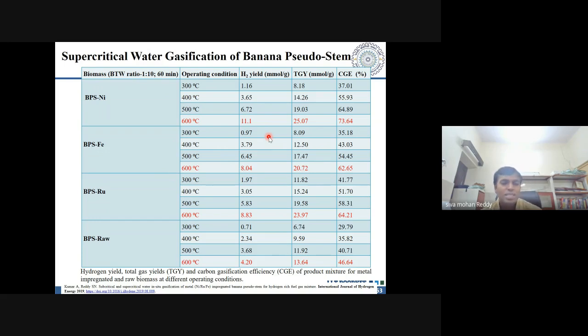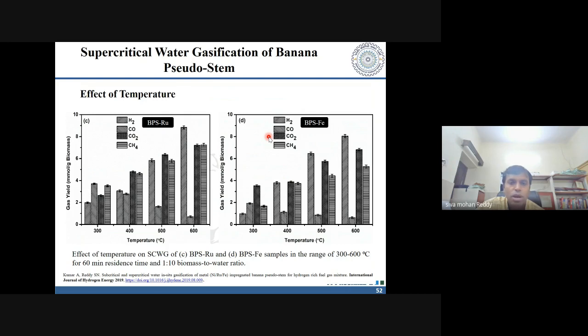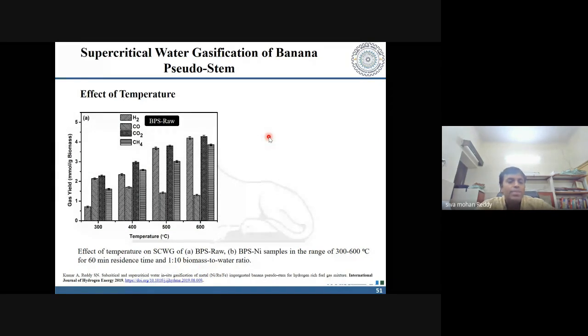So now all these experimental results convey to us that the presence of these nanometals in the biomass during the impregnation stage enhanced the quantity of not only the total gas yield, but also improved the carbon gasification efficiency. Along with that, they have selectively promoted the hydrogen gas yield to a greater extent, almost 2 to 3 times that of your raw biomass that we are talking about.